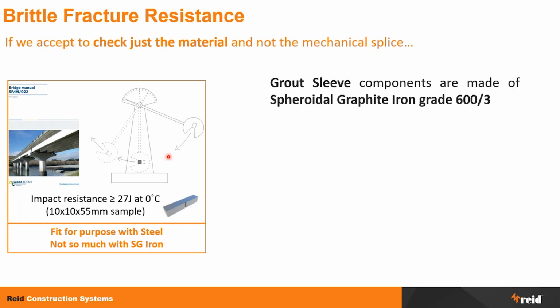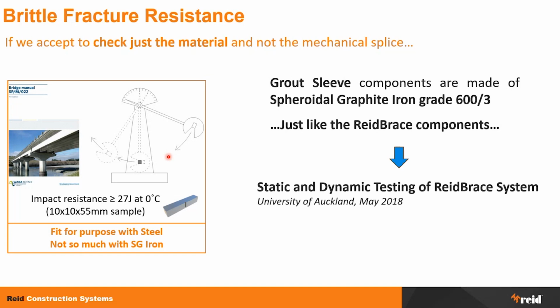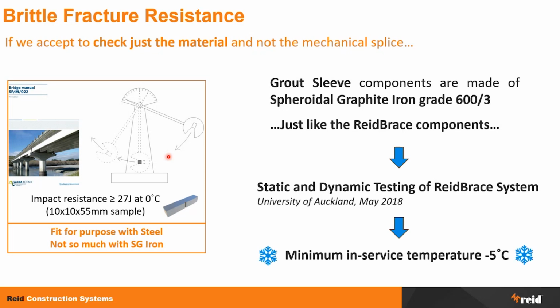So how we handle this is that we consider that the fittings like grout sleeve are made from spheroidal graphite iron grade 600/3, and Reid brace components, they're also manufactured by Ramset now, Ramset Reid. Reid brace are made of the same material, exactly the same grade. And this system, the Reid brace system, was extensively tested by the University of Auckland in 2018. It was subject to static and dynamic testing, and also to impact loading at freezing temperature of the components. The outcome of these tests was that the minimum in-service temperature for the system would be suitable as -5 degrees Celsius.